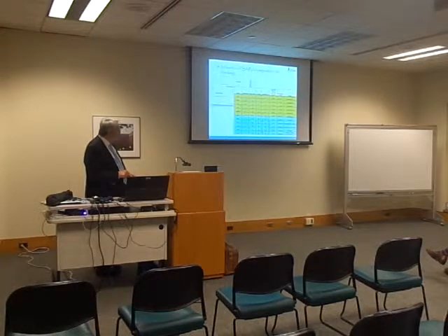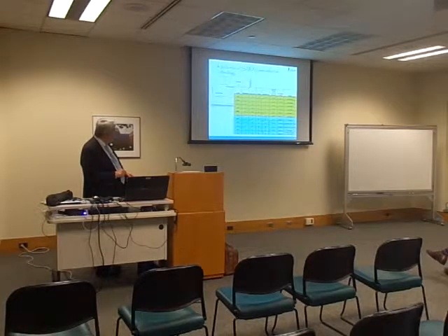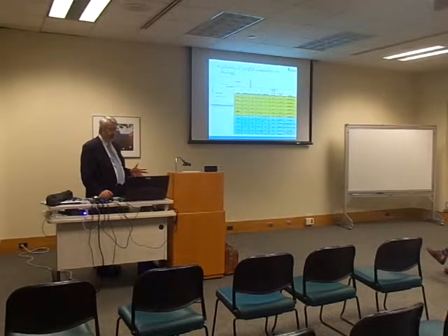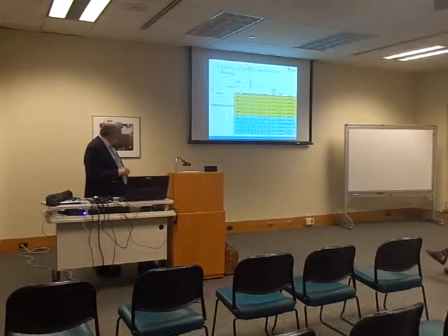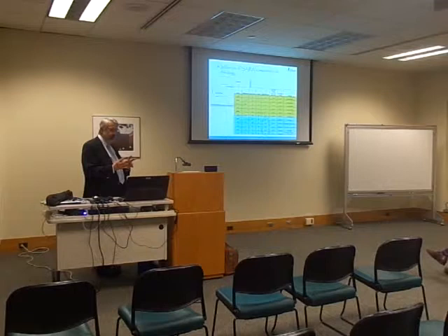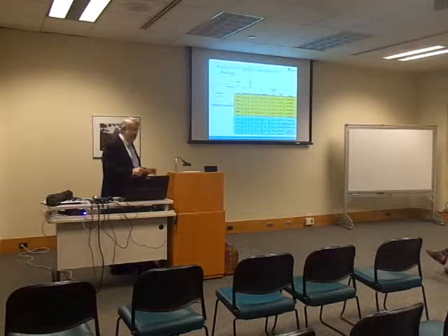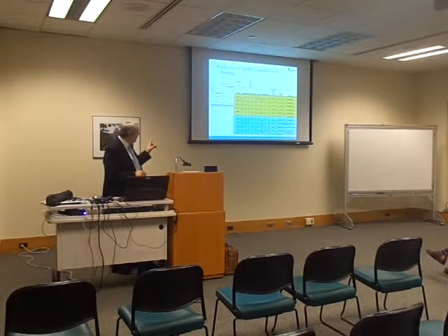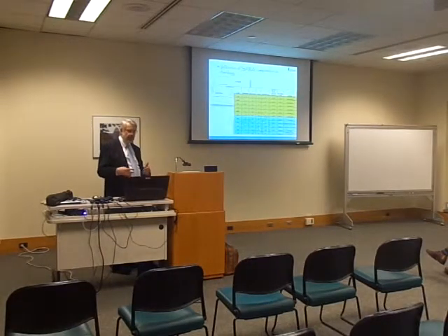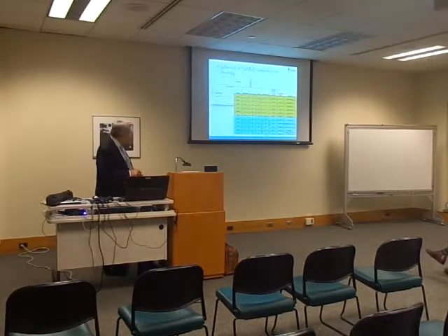And you notice that the industry is developing rejuvenators where their asphaltenes are small percentages of the total. Why? Because that guarantees a soft material. If you have too many of these large molecules, they create a stiff material. The reason there are many here is because these are oxidized. These were not virgin bitumens, unaged bitumens. It's the oxidation that raised the percentage of this particular chemical component.